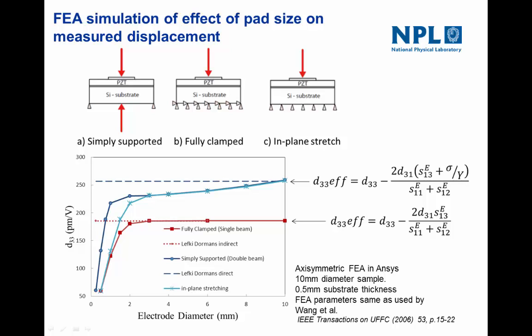To reinforce this geometry effect, here are finite element simulations for three different cases: on the left the simply supported system (double beam), in the center the fully clamped system, and on the right the in-plane stretch case where the bottom is clamped against bending but can still move in-plane. The graph shows displacement as a function of electrode diameter for these different clamping conditions, and it varies from 50 to 250. There's only one constant region: above about two millimeters on the fully clamped sample — which is what led Wang to suggest using two millimeter pads or greater. But as we've shown, it's almost impossible to fully clamp the sample in practice.